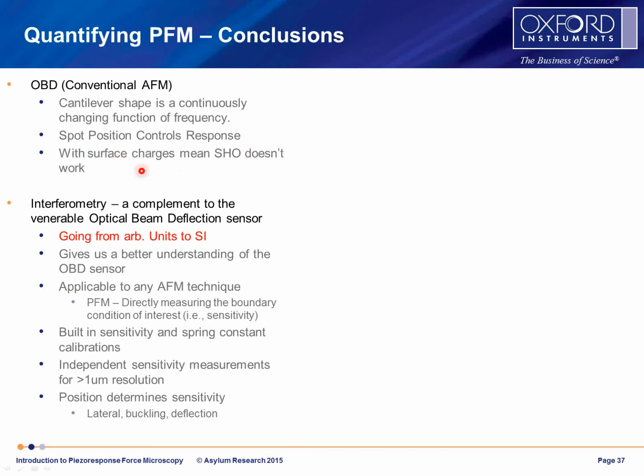In the case of materials where there is a surface charge, you have to use the simple harmonic oscillator very sparingly, and you may actually need to turn to an Euler-Bernoulli model to take the transfer function of the cantilever properly into account. I did show you at the very end a little bit of the results from some new interferometry experiments where we've combined an interferometer with a conventional optical beam deflection sensor in our Cypher AFM.